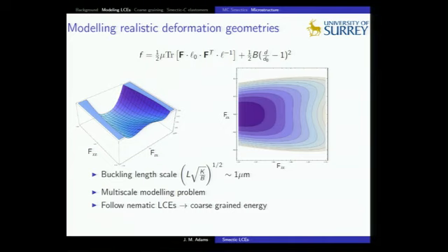Well, we can look at the free energy that I mentioned before, and if you plot it out as a function of the deformation parallel to the layer normal in the z direction, and then a shear, you can see that it's a non-convex energy, which is, again, the signature that you're getting some sort of microstructure formation, as we saw in the nematic phase. So this is just a contour plot of this surface here, and you can see the fold that I've shown here appears in the level sets over there.